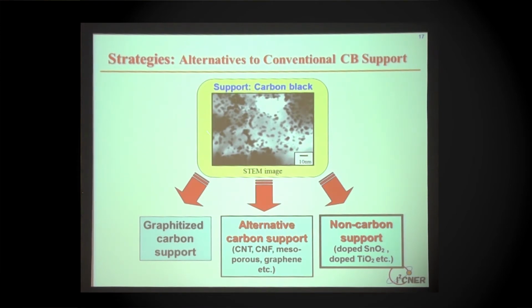And this is a typical micrograph of the electrocatalyst. Of course, we have small particles of platinum with a diameter of 3 nanometers. And these platinum nanoparticles are dispersed on the surface of carbon black as a state-of-the-art conventional electrocatalyst. Now we have three different possibilities and strategies. One is the typical method which is widely used, for example, in automotive companies: graphitizing the carbon support. This is the straightforward solution.